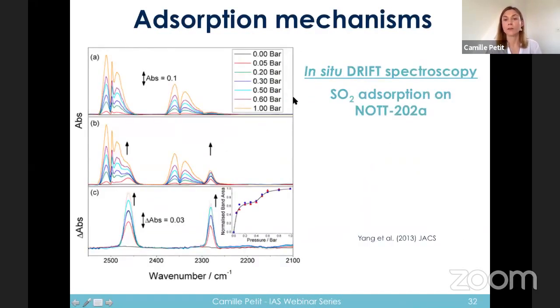Another technique here is that of in situ DRIFT spectroscopy. And I give here the example of SO2 adsorption on a given MOF, which is called NOTT-202a. And in situ DRIFT is a common technique used to look at solids or powders formed in different atmospheres. Okay, and so at the top here, you're monitoring for different pressures of SO2 how the spectrum looks like. And now you're introducing in the middle panel here the MOF, and you see that there is a difference because we have specific bands related to SO2 adsorbed in that specific MOF.